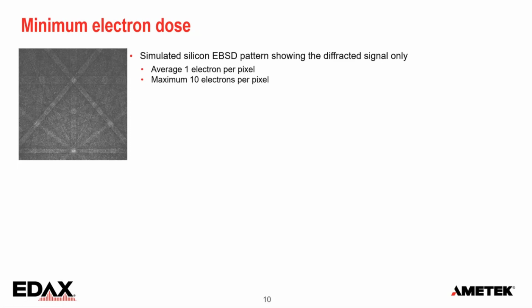Okay, so we can quantify this. We can see how many bands or how many electrons we're going to get. Now the question is, how much do we really need? And this is a simulated diffraction pattern from silicon, where on average, there's only one electron per pixel. So a lot of the pixels in this image are just black. There's no signal at all. And the maximum is down here at the bottom, where we get 10 electrons per pixel. And this pattern looks quite nice. And this is with a few tens of picoamps in the model. So that should be possible to get indexable patterns there.